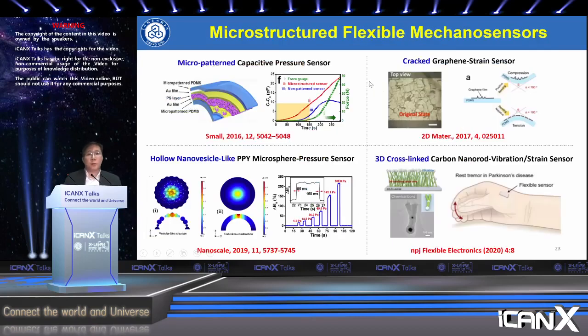And with this microstructure design, we developed a series of different types of flexible mechanical sensors. For example, we use a micro-patterned PDMS layer as a dielectric to make a capacitive pressure sensor. We get an extended sensing range for this microstructure sensor compared to non-patterned sensors. And also we use the CVD growth method to get cracked graphene grown on the two electrodes, which has selective sensing of the strain directions.